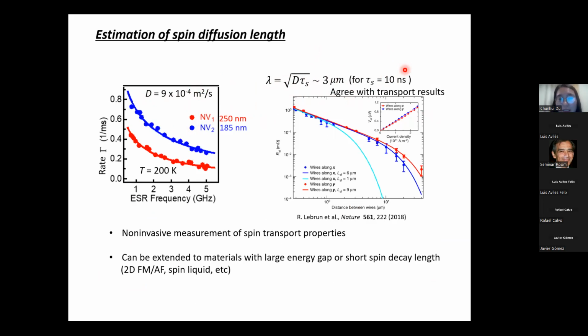micrometer, and this length scale is also in agreement with the transport measurement result using the non-local measurement geometry based on alpha iron oxide. So this confirms the validity of our method.